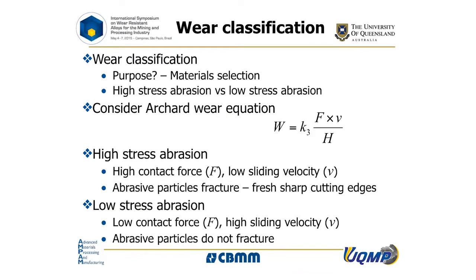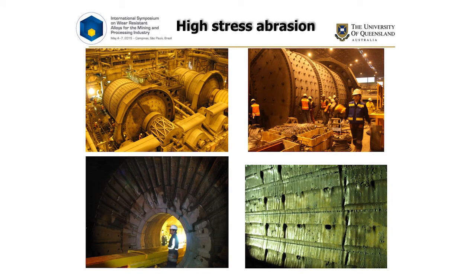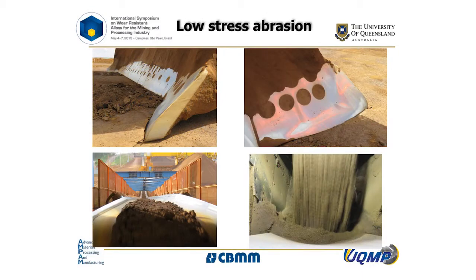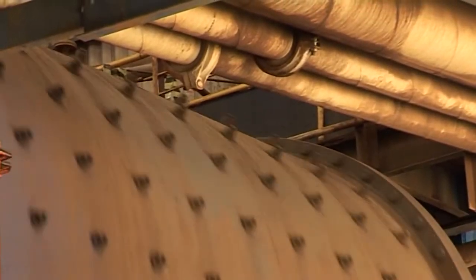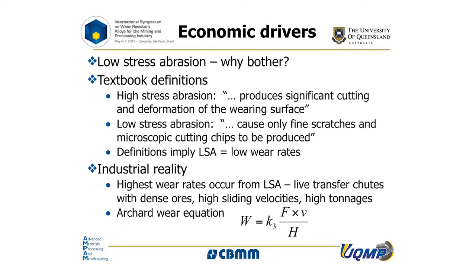Forgings and castings. Whilst this session was primarily concerned with forging and casting products, their design, manufacture, and metallurgical blueprints, we also learned more about the classification of abrasive wear mechanisms and the challenges of establishing meaningful laboratory tests which can accurately predict performance in specific applications. It was demonstrated that textbook classifications don't always follow or align accurately with practical experience, and with reference to a ball mill case study, it was revealed that the only reliable way to assess likely wear in a ball mill is to do tests with a ball mill. The ASTM pin abrasion test was unlikely to provide accurate predictions, thus underlining the point made earlier about developing new application-specific tests.